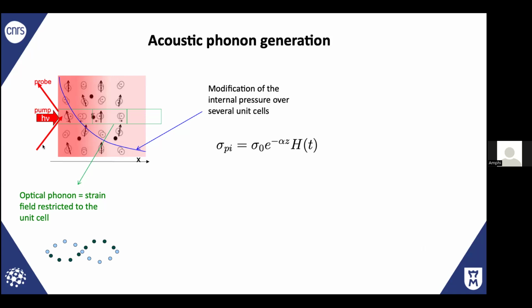And so that gradient can be the gradient of the light absorption, but the electrons can move as well. But there is always a gradient. And this is a key element for the generation of acoustic phonons. So basically, the photo-induced stress, which is like a photo-induced pressure, is usually first described by such an expression, which is here just the profile of the light penetration.